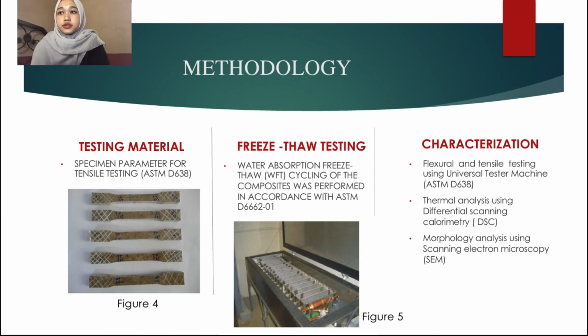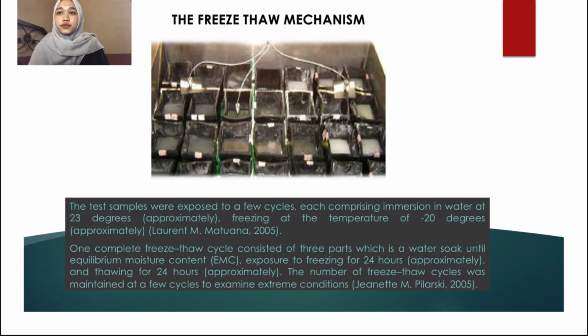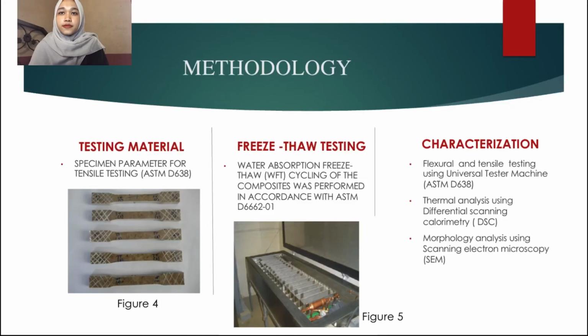The characterization: first, flexural and tensile testing using a Universal Testing Machine, ASTM D638. Then, thermal analysis using differential scanning calorimetry, DSC. And lastly, morphology analysis using scanning electron microscopy, SEM. For freeze-thaw testing, water absorption and freeze-thaw cycling of the composite was performed in accordance with ASTM D6662-01. And for the material specimen parameters for tensile testing, ASTM D638 is used.